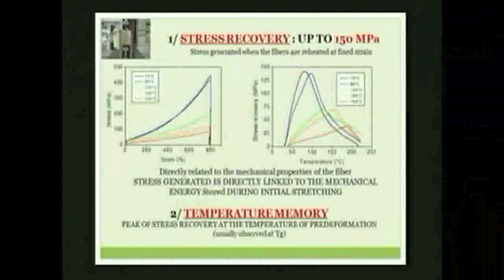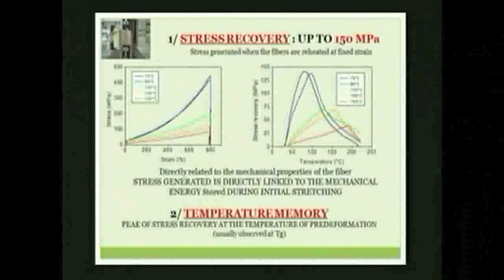We made the video for fun, but then we measured the stress recovery with this setup. It's a furnace in which you can stretch the fiber and then measure the forces. It's a tensile load setup. And when we do this, we have measured stress recovery up to 150 megapascal. Remember, for conventional polymer, it's a few megapascal. So we have a much higher effect. And the strain is also very good.